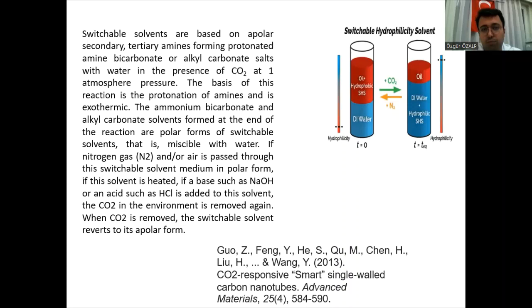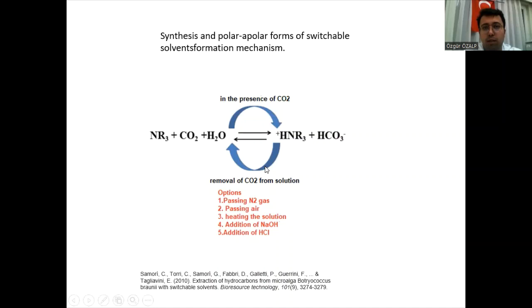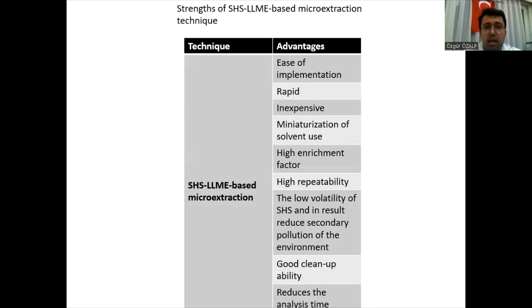And then you can see the synthesis and the polar-apolar switchable solvent formation mechanism in the presence of carbon dioxide. These are normal chemicals, and carbon dioxide is environmentally friendly. If you add carbon dioxide, it becomes protonated amine bicarbonate. If you cannot use carbon dioxide, you can use nitrogen gas or air with heating of the solution, and we can use sodium hydroxide or hydrochloric acid. You can have five options. For switchable solvent liquid-liquid microextraction, the advantages are that it is rapid, inexpensive, has high enrichment factor, high repeatability, low volatility, good cleanup, and reduces the analysis time.